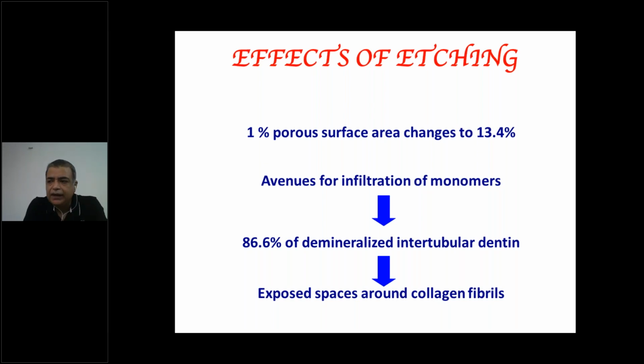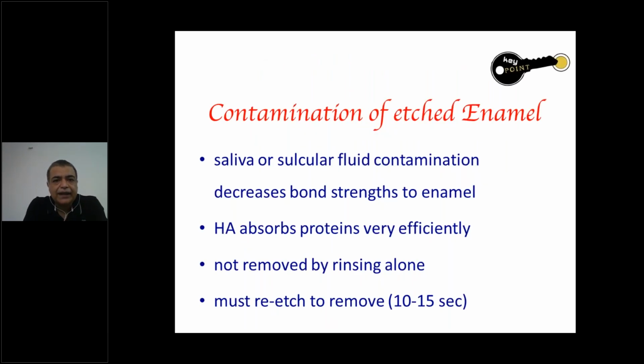In dentine, you have intertubular dentine, and the intertubular spaces open up, whereas in peritubular dentine, the dentine tubules open up and also the surface energy decreases. But the key point in enamel etching or dentine etching is, if after etching the patient has spat, or rinsed his mouth, or the tooth has come in contact with saliva or sulcular fluid, you will not have effective bonding, because hydroxyapatite as well as dentine has the power to absorb proteins very efficiently, and they cannot be removed by rinsing alone. So it is very important that in case the etched enamel or dentine is contaminated, you must re-etch the surface again.